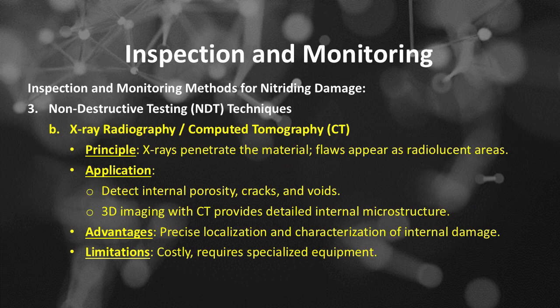The next NDT technique is X-ray radiography or computed tomography, or CT. Its principle is that X-rays penetrate the material, and flaws appear as radiolucent areas. Applications of this radiography or CT technique are to detect internal porosity, cracks, and voids. 3D imaging with CT provides detailed internal microstructure. The advantage is precise localization and characterization of internal damage, and the limitation is that it is costly and requires specialized equipment.